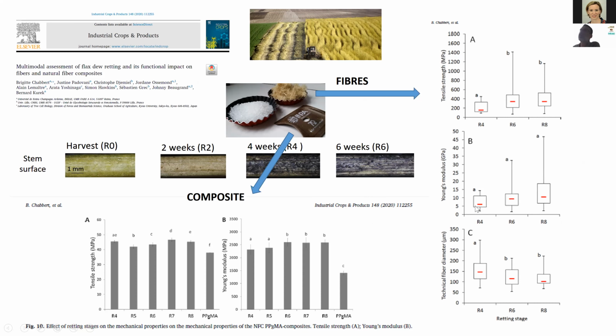You see that if you consider the Young modulus, for instance, of the fiber bundle, there is not so much difference because the variation is very strong, but some parameters can be different, such as the tensile strength and even the diameter of the fiber. These two parameters can have an impact afterwards if you make composite material. This has been performed on small test pieces to test the mechanical properties of the material. And we see that the effect is quite different relative to the retting stage. If you are retting too much, it's not good.